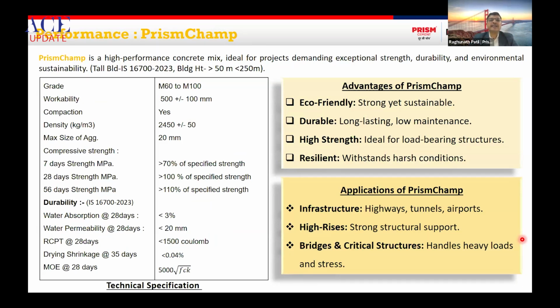For tall structures, buildings more than 50 meters and up to 250 meters in height, along with strength, the durability parameters are very, very important. That's why when we design the mixes, we need to take care of all the durability parameters. In case of workability, we generally keep 500 plus minus 100, and we generally use 20 mm aggregate. Strength, as per the design parameters, we target 100% at 28 days. But because of the lower water content and higher binder content, the strength can continue for a longer period, and after 56 days it generally gets 110 to 115%.